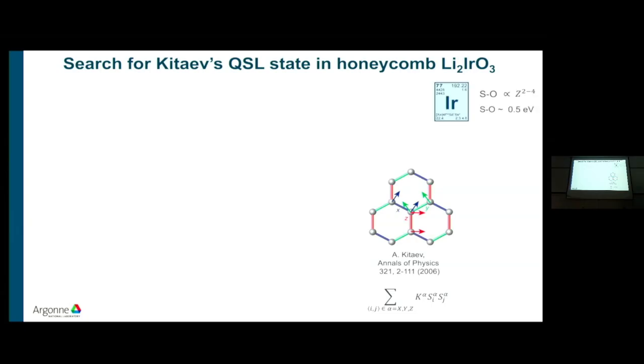So we are looking at these iridates because iridium has very strong spin-orbit coupling. When you ask how to get spins to align along a certain direction of the lattice or a bond, you want spin-orbit coupling. This particular system has iridium 4+ valence states, a low-spin 5d5 electronic configuration. The wave function of this 5d state is such that if you have edge-shared octahedra, it can be shown that the isotropic Heisenberg exchange, which is the typical way you couple spins in magnets, cancels out. It requires exactly 90-degree superexchange interactions, and it has to do with having two different exchange pathways going on the top and the bottom. There is some quantum interference that cancels this isotropic exchange.